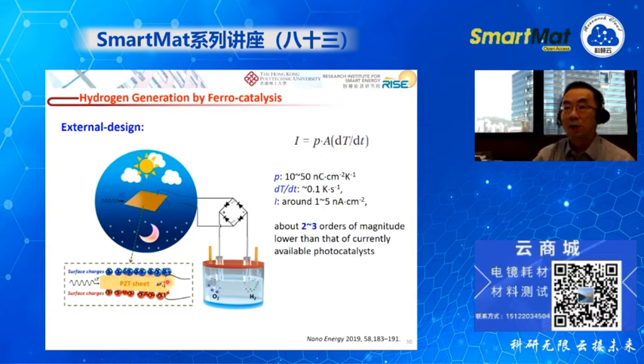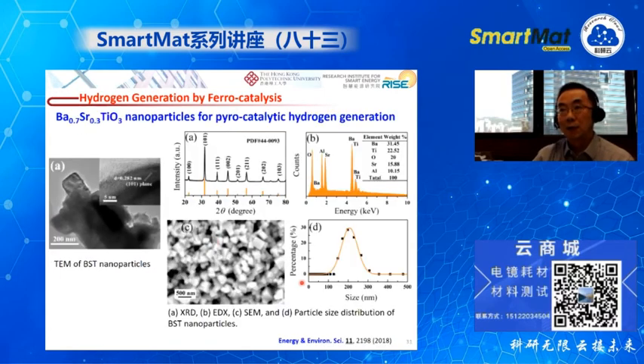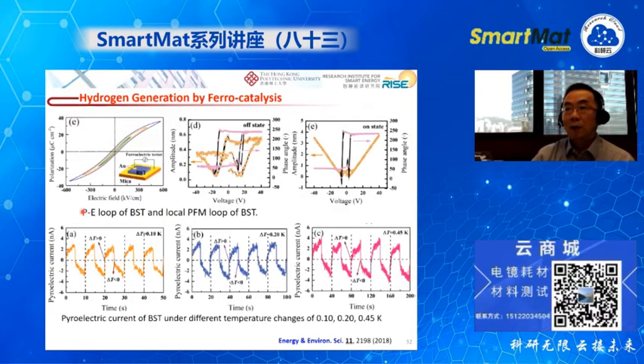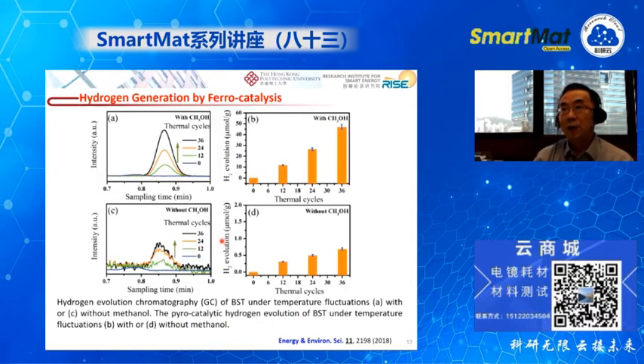The purpose of nanoparticles is that, compared to the bulk material, we have a much larger surface area, and for the pyroelectric material and the piezoelectric material, the charge is generally only on the surface. So the surface area is very important for the enhancement of pyrocatalysis. So this is the first example: we fabricate these barium strontium titanate nanoparticles. Then we characterize their ferroelectric properties, and we also measure the pyroelectric current released when we cycle the temperature. When there is a cyclic temperature change of the material, we can get a pyroelectric current release from the material. Then we do the catalysis.